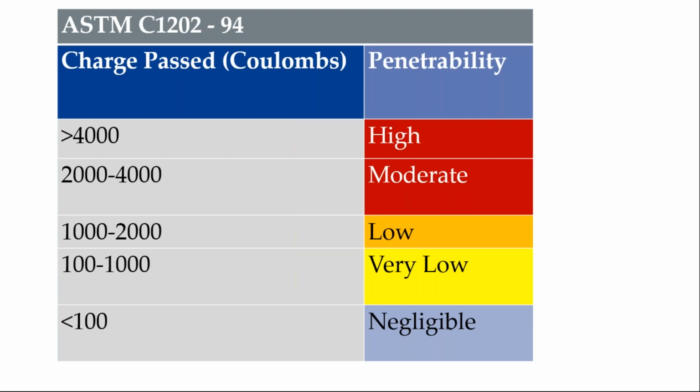And as all of us know, there are some structures where they say that we want 1500 coulombs and it has to be higher compressive strength. Now that is where you have a challenge in selecting the right type of constituent for such a concrete. Now imagine that you want a durability value measured through RCPT as 1500 and a higher compressive strength both together, it can be quite challenging. So that is where you need to have the kind of trials that we do at site, where you will find that the concrete has to be different from the conventional concrete.